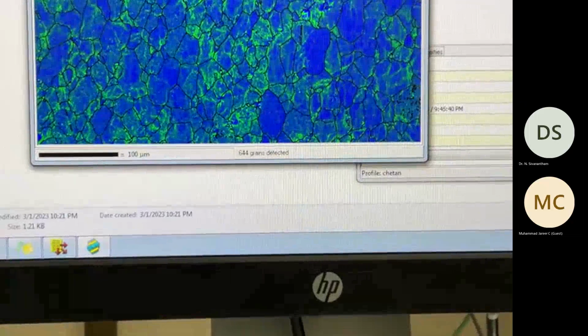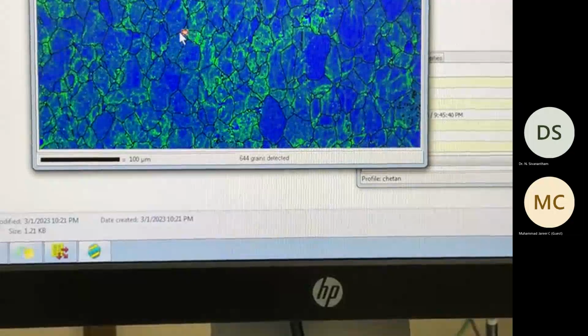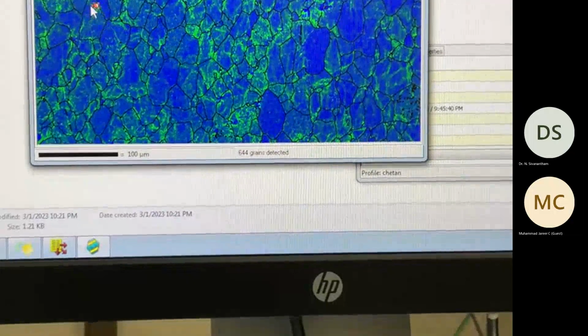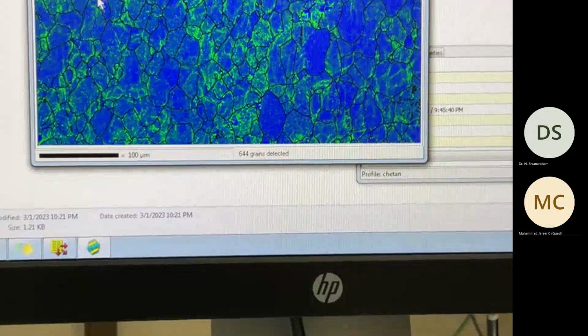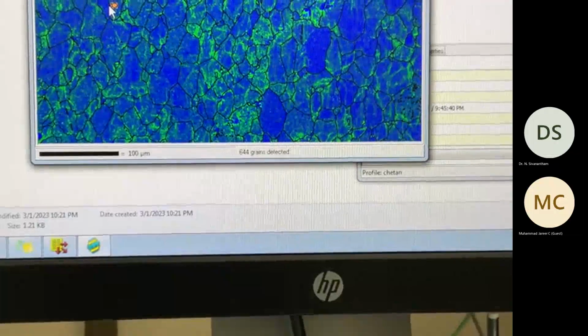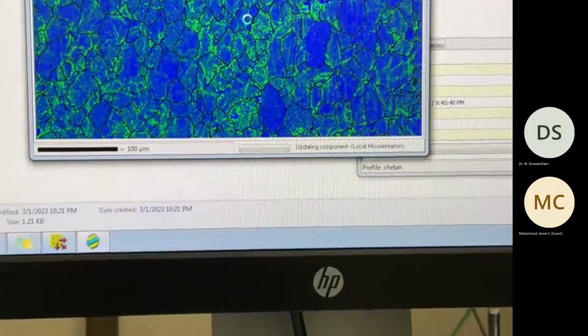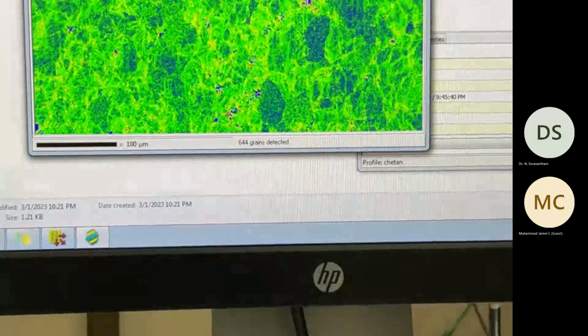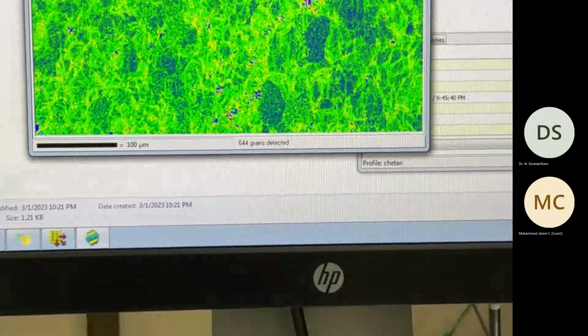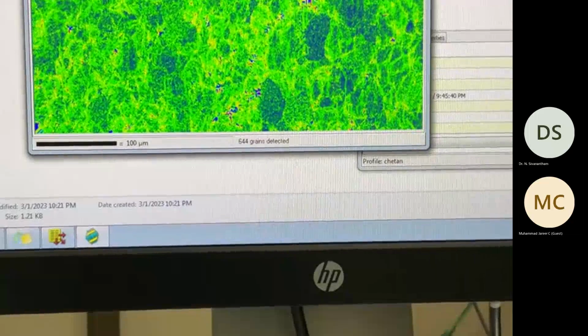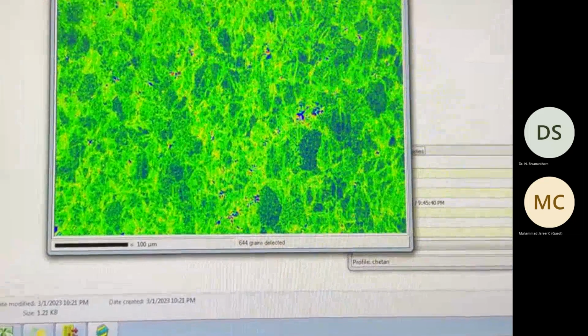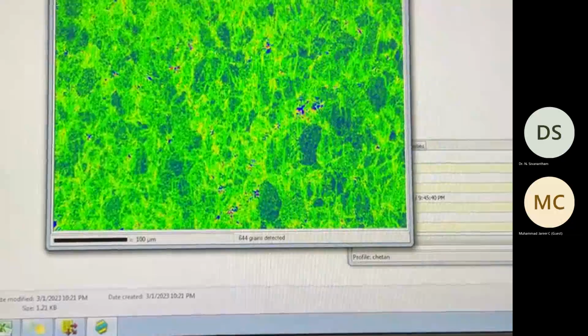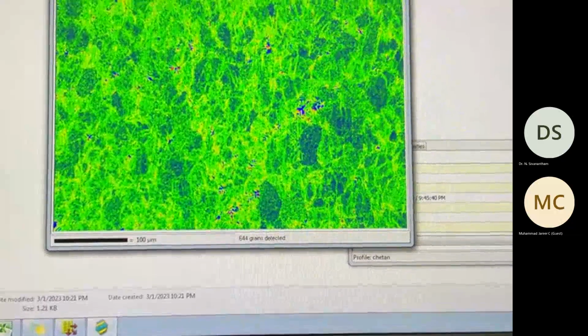We can find out how the Schmid factor is varying, how the strain is. So you can see in this region, a few of the grains have more strain, and a few of the grains have less strained region. All this can be seen in EBSD, and line maps can be plotted using this. It will take some time for plotting line maps. Whatever you are interested in, how the grain boundary is varying or how the misorientation is happening, all this you can see.